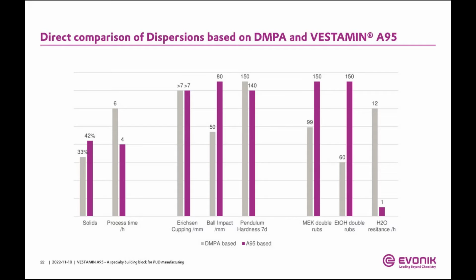So here we also see that, I would say, both are convincing, both are perfectly fine. We have an Erichsen cupping of 7 millimeters. We have a slight difference in the ball impact, but I would not overestimate this difference. Maybe the advantage for the A95 looks bigger than it is. Actually, those values are pretty comparable. Also, the pendulum hardness after 7 days, 150, 140, very close together. In this particular case, we have even for the A95 a higher chemical resistance in terms of MEK and ethanol double rubs.